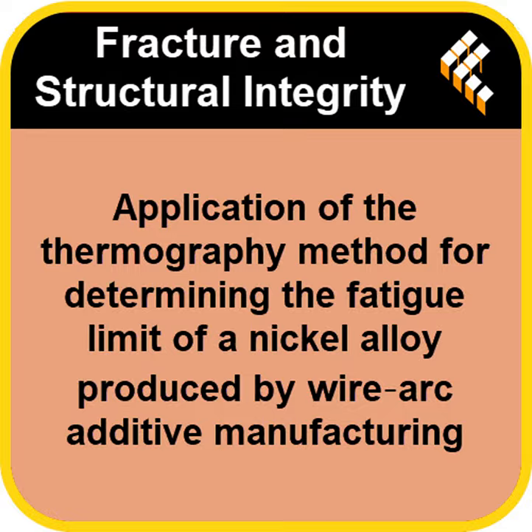The sources mentioned 3 stages of heating. Right. So typically when you start stressing a material, the temperature goes through 3 phases. Stage 1 is that first quick temperature increase. Stage 2 is where it stabilizes, heat in equals heat out. And stage 3 is that runaway heating right before it fails. And waiting for stage 2 for that stabilization would still take too long. Way too long. And that's the secret to the acceleration.